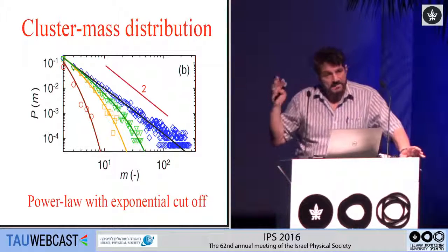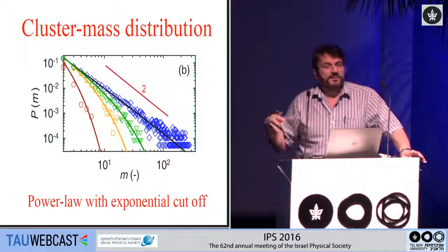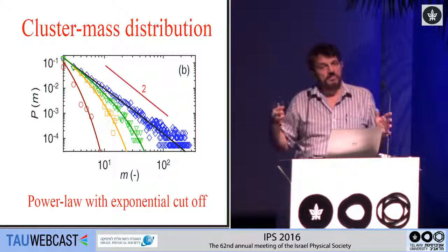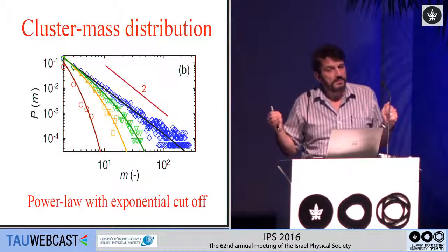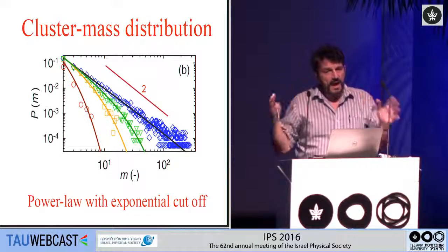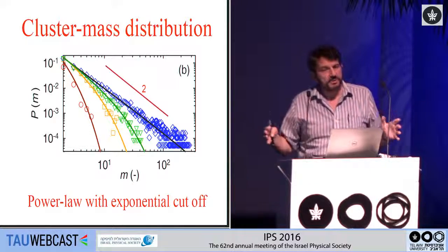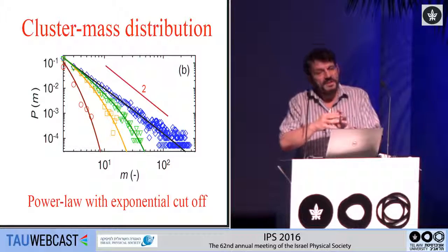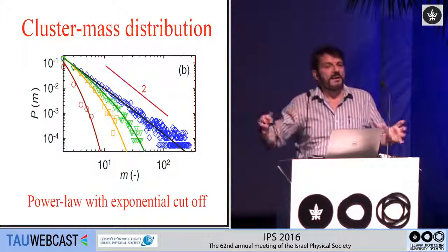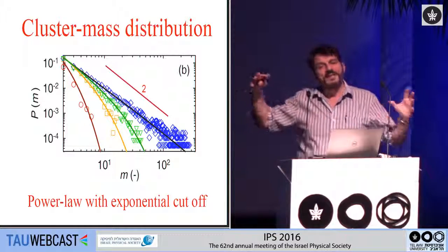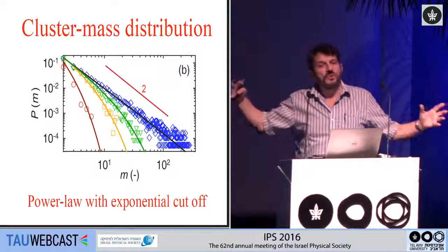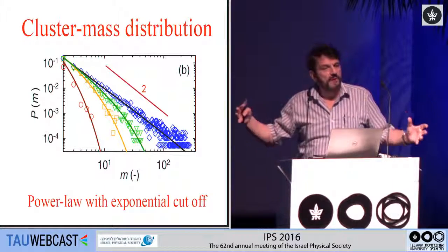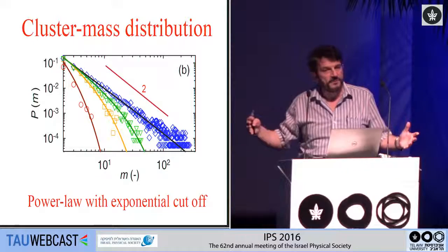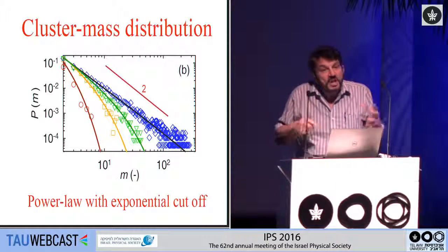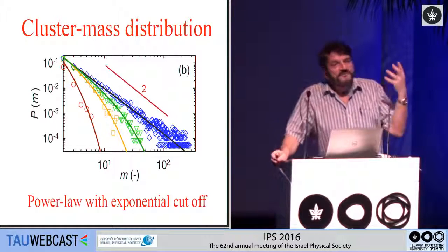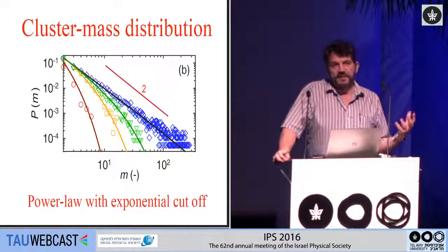Actually, if you look at a variety of theories for understanding power law distributions, for example, the Smoluchowski theory, whenever you have a power law of 2 for the mass distribution, what that means is that you can extend through all space. You can gel. You can form a connected network that extends through all space once you have a mass power law of 2. And this is, in fact, one sort of physical way of thinking about what's happening.